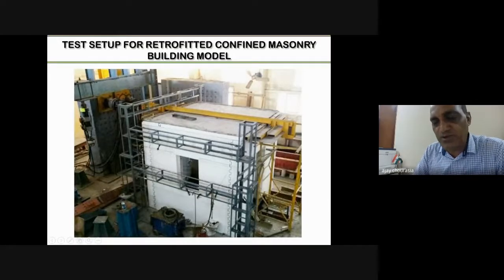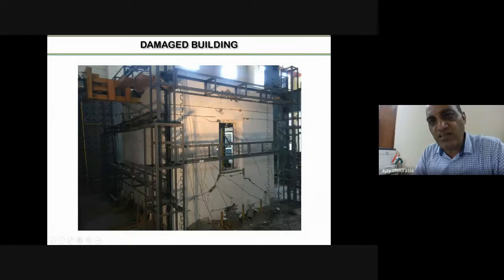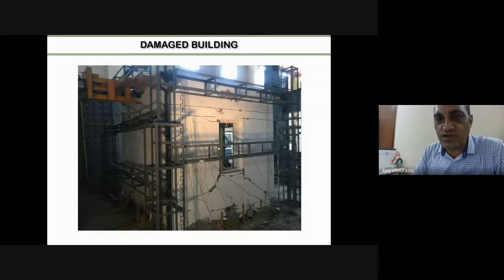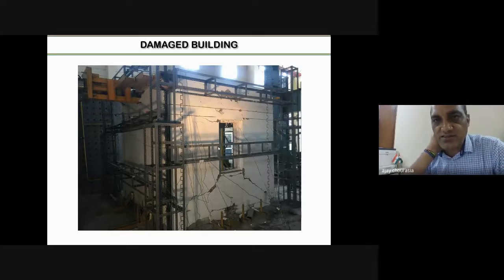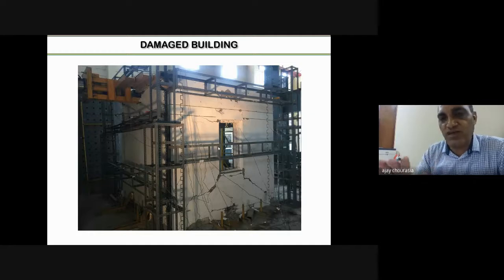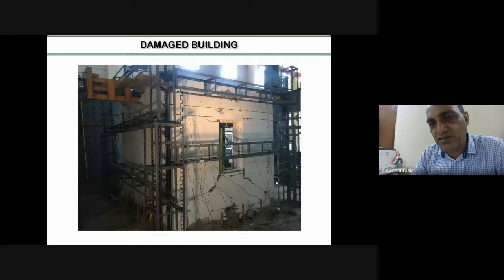Again, a similar experimental protocol was applied to conduct the test on this model, and at the higher loading we could see the damage pattern seen in the confined masonry in terms of cracking and spalling. We have normally seen the cracking generally start from the corners of the openings in the in-plane wall and march towards the corners, and these cracks pass mostly through the mortar joints, sometimes through the masonry units also. At the higher loading, crushing of the concrete at the toe region and bending of the longitudinal reinforcement of the column take place.